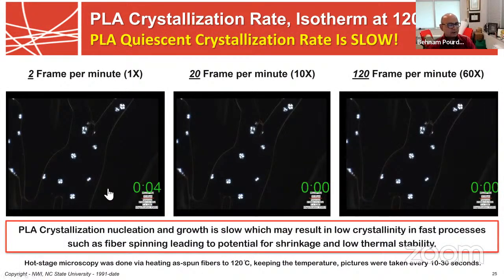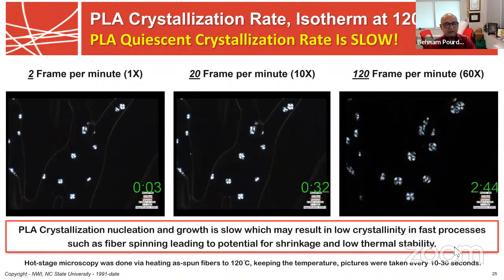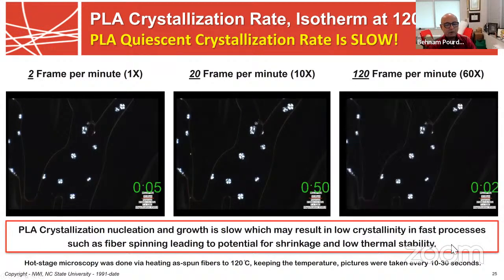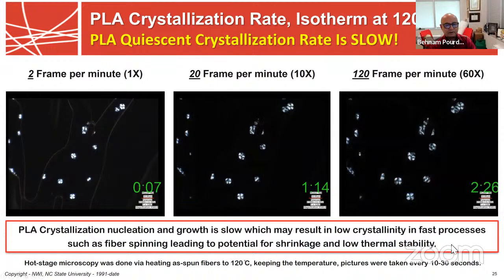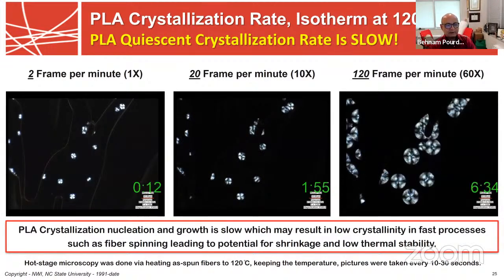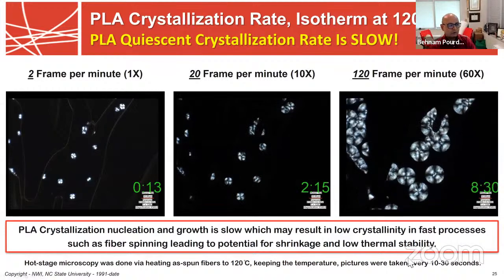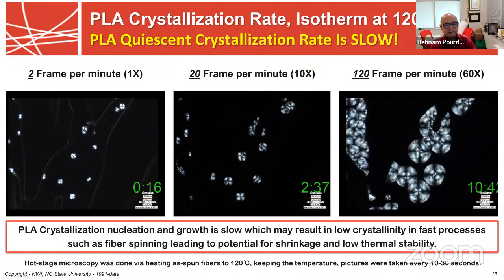So let's look at the crystallization of these materials. So if you look at PLA by itself, and I'm going to accelerate these. So this one is accelerated, and it takes an awful lot of time for the material to crystallize. And this is a post-treatment process on fibers. So these are fibers that you're looking at actually, and incredibly slow.